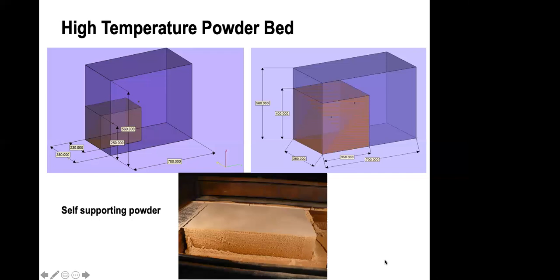So these are unique features available only to high temperature powder beds, as far as I'm aware, and quite unique when we talk about these reduced mode chambers, where the powder is self-supporting and is able to build in a smaller area. If you think about some of these polymers, they are highly expensive, and having to build components, or even small parts, in such a large bed will require a lot of powder. The fact that we can operate in a reduced mode without changing the performance of the system, the temperature gradients and everything else, is quite unique and beneficial at the same time.